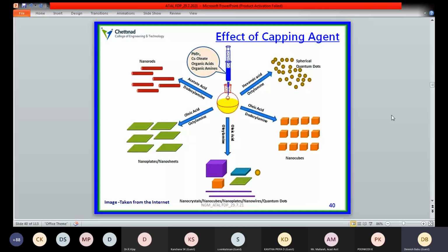So when we synthesize this perovskite material, the traditional methodology used to fabricate it is called the hot injection method. So in the presence of high temperature solvents, we can easily inject cesium oleate and lead bromide, with organic acids or organic amines as capping agents, to fabricate these cesium lead based perovskite systems by the hot injection method. In this slide, I have mentioned the various capping agents, acids and amines, like acetic acid, dodecylamine, oleic acid and octylamine, and the traditional one, oleic acid and oleylamine, oleic acid and dodecylamine, and hexanoic acid and octylamine. If we use these combinations, we can easily get spherical quantum dots of these cesium perovskites.